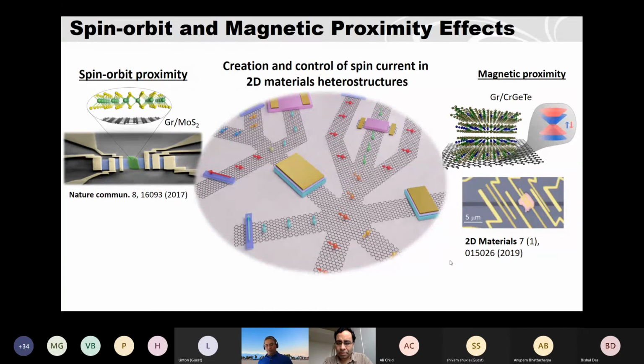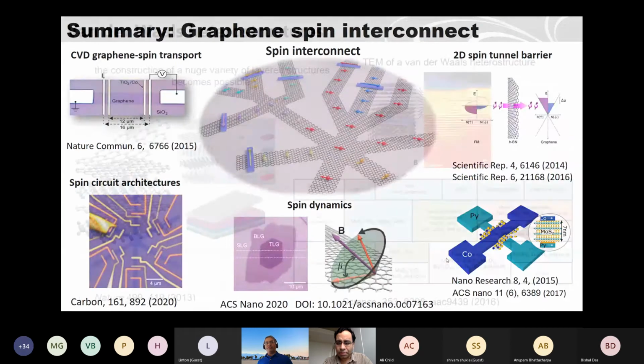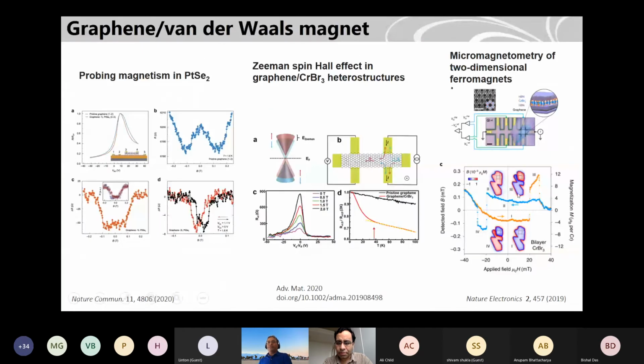For example, Andre Geim and Novoselov's group are quite actively studying this. I showed one of these papers, from Manchester. You have these graphene Hall bars, a similar structure to what we usually make. They put a flake of chromium bromide on it. There are some domain walls, and they could detect the magnetization of these domain walls from the Hall measurement. So it's a stray magnetic field that comes into the picture with the graphene Hall structures.